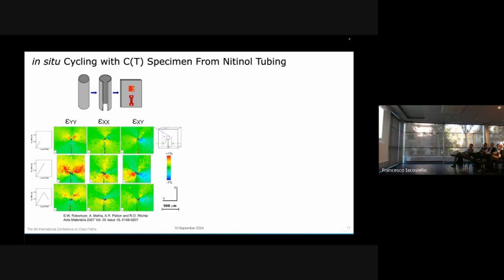This first image is just the actual YY strain. The loading path is close to 7.5 MPa root meters, then goes up to 15. Here, you see immediately it's exactly what we'd expect: the strain fields around that crack are increasing. Again, the black area here is the martensite that's transformed.